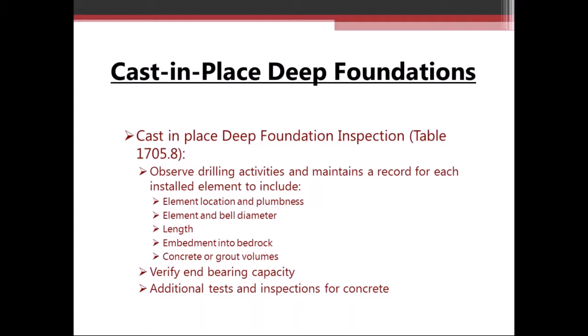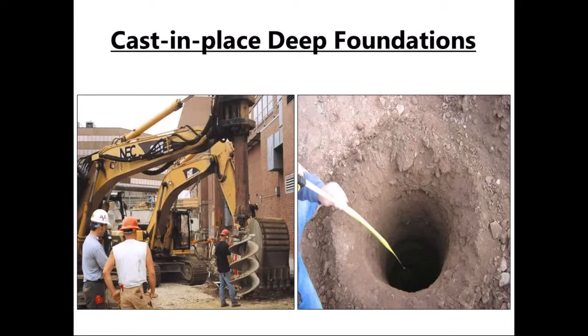Typically, especially with the drilled piers and the micro piles, they're going to be embedded into bedrock. So the inspector is going to verify that the design embedment into the bedrock is achieved through visual observation on site, as well as the information from boring logs contained in the geotechnical report. And then they're going to also monitor the concrete and grout volumes that go into those deep foundation elements. And then there is some additional testing as far as concrete or grout, whichever is used to cast the units.